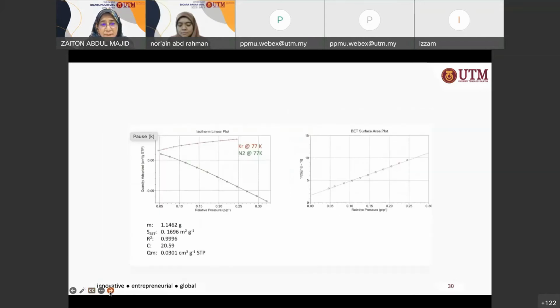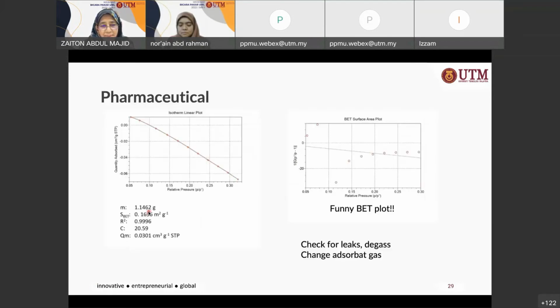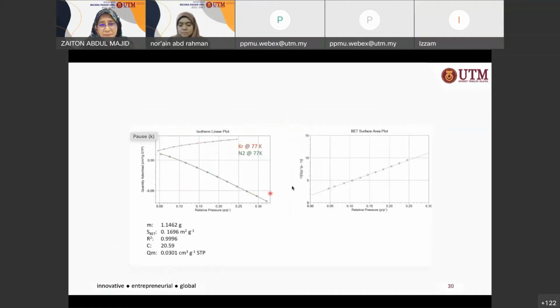So what they did with this particular sample, let me just go back here. They used the same mass, 1.1462, but they changed the adsorbed gas to krypton. So this is krypton, and it looks better. This is nitrogen at 77 Kelvin, krypton at 77 Kelvin. So the isotherm linear plot is better. There is an increase in the quantity adsorbed with increase in pressure. This makes better sense.